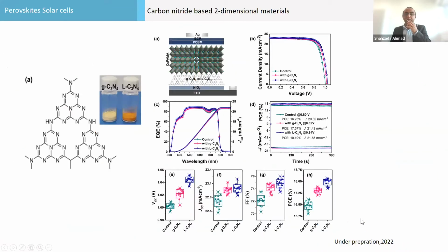We are collaborating with King Fahd University on carbon nitride, because we learned that the 2D materials work very well. We are using them as an interlayer. So why not functionalize the 2D material? Something like NH2 will have a double effect. It will do passivation also, and with this 2D material it will increase the stability.